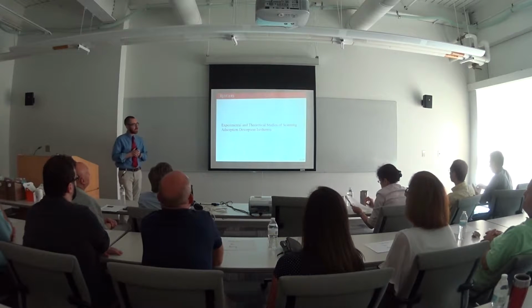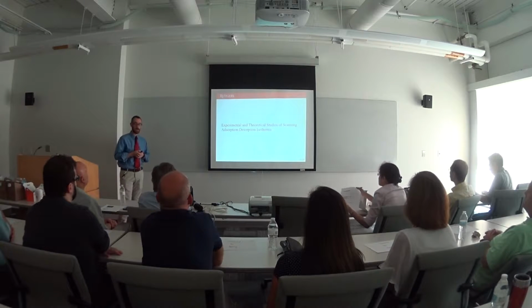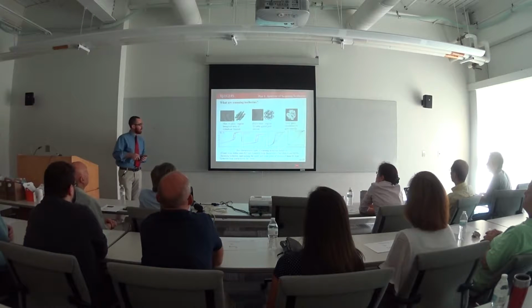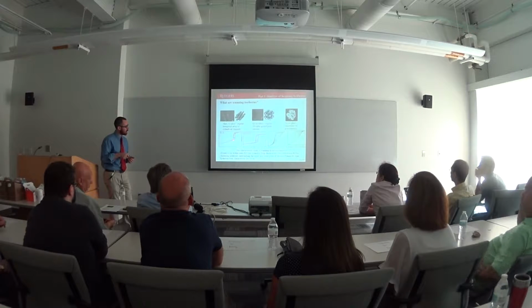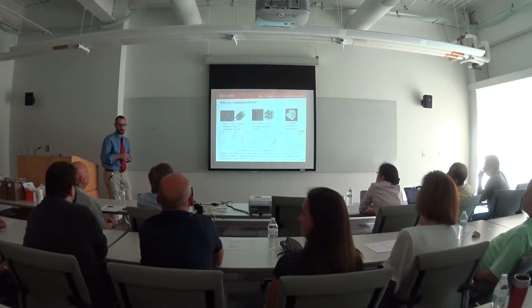In the first chapter of my dissertation, I looked at a special type of adsorption and desorption isotherm called a scanning isotherm. So what's a scanning isotherm? Scanning isotherms, so this is our main hysteresis loop. A scanning isotherm occurs when, if we go up on the adsorption branch, and all of a sudden we decide we want to go backwards and desorb instead of going all the way to capillary condensation, we get this additional curve which is inside the main hysteresis loop. It goes from the adsorption curve all the way to the desorption curve. And we can do the same thing from the desorption curve back up to the adsorption curve.